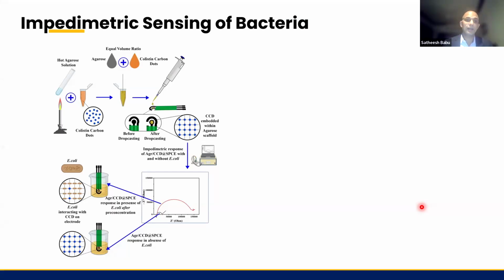So here in this example, we developed carbon dots functionalized with an antibiotic. For example, colistin, which is specific for gram-negative organisms, was used to functionalize the carbon dots. Here, typically we use nitrogen sulfur co-doped carbon dots, and that was immobilized on the electrode using agarose. Agarose gel we used to immobilize the carbon dot on the electrode surface. So we have the working electrode of the disposable strip, which is modified with the carbon dots. Then we dip that electrode in the solution that contains bacteria, and we applied a pre-concentration potential of plus 0.5 volt for 3 minutes.